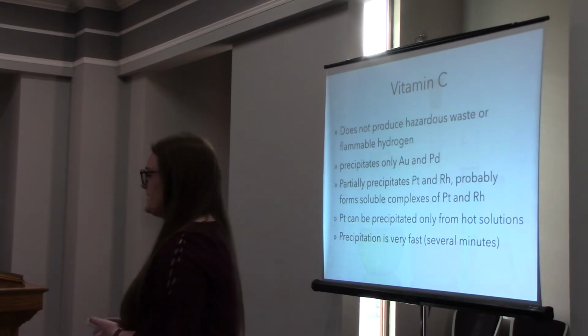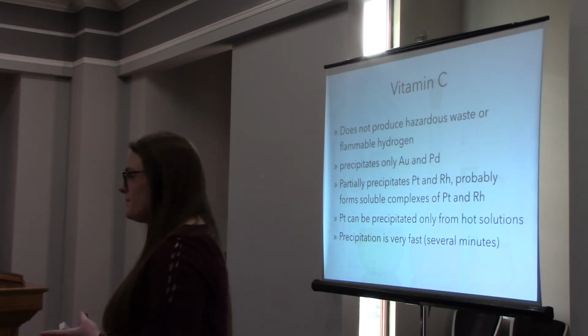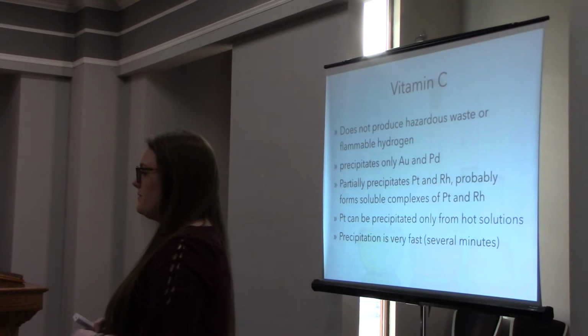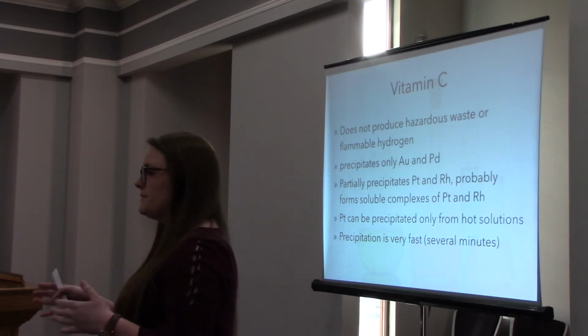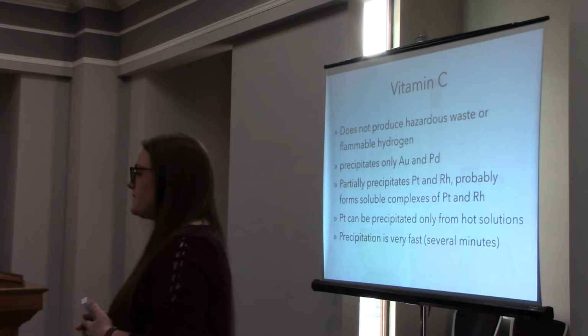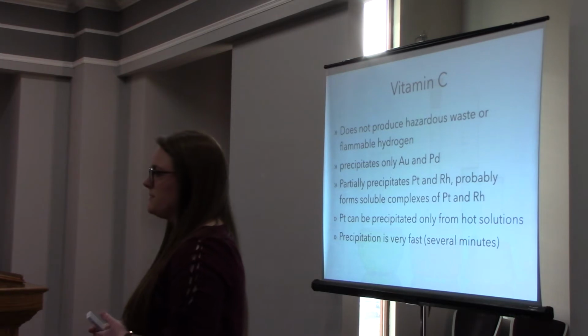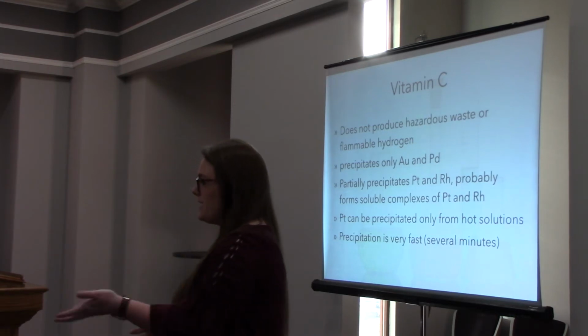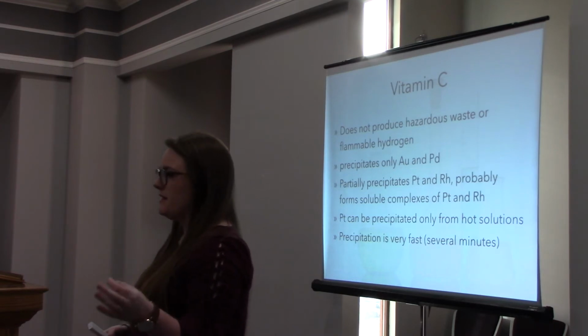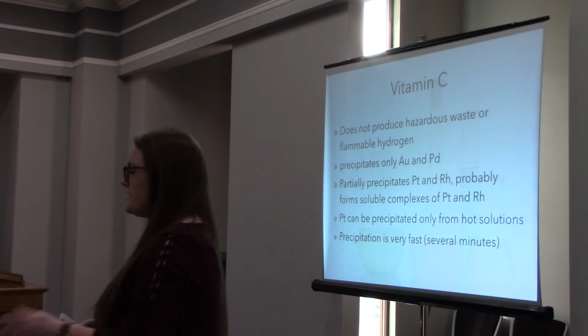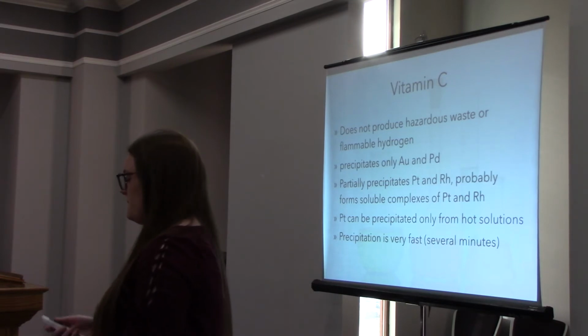So then vitamin C does not produce hazardous waste. It does not produce flammable hydrogen. It does precipitate only the gold and the palladium, but it partially precipitates platinum and rhodium, and that's probably due to soluble complexes that it forms with platinum and rhodium. But platinum can be precipitated with only the hot solutions. And then this reaction goes really quickly. It only takes a couple minutes to do.